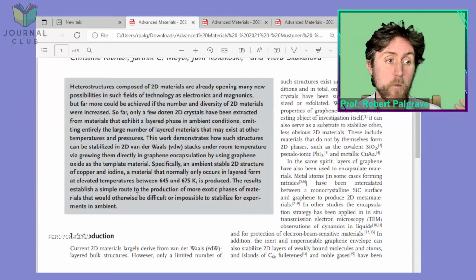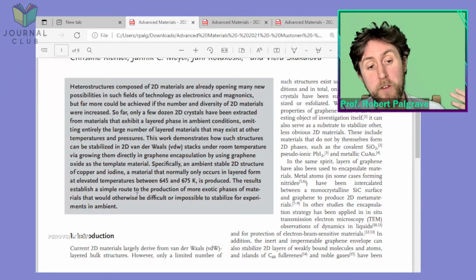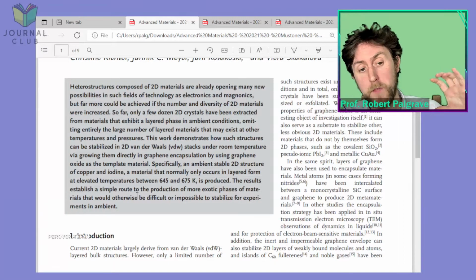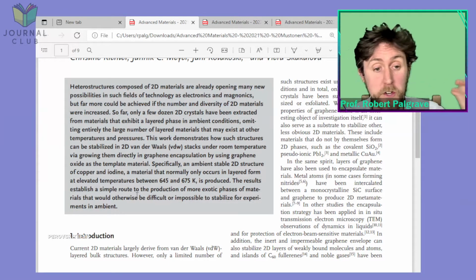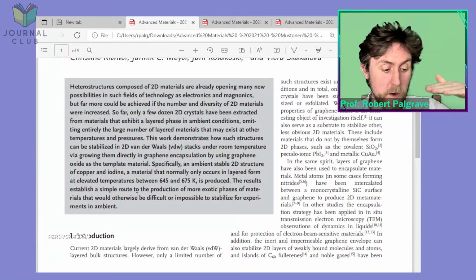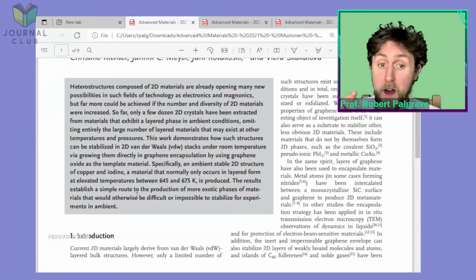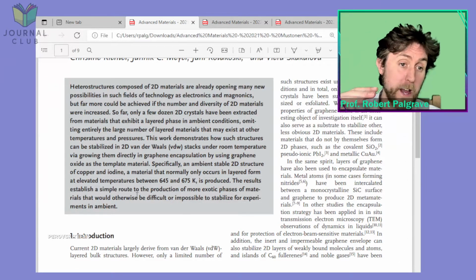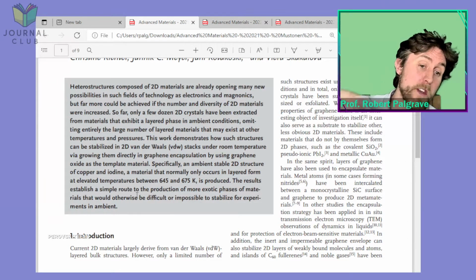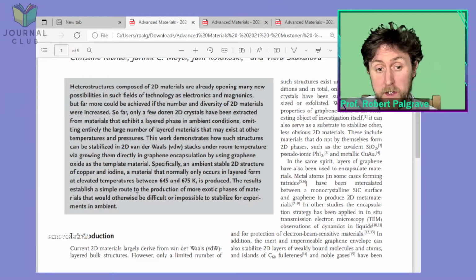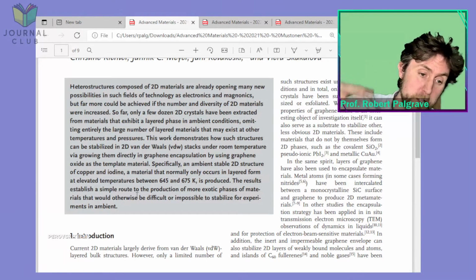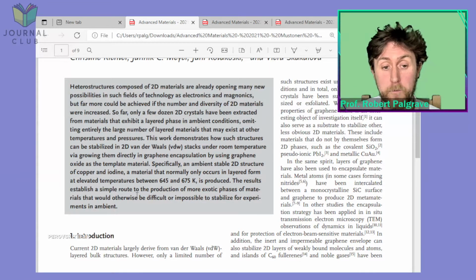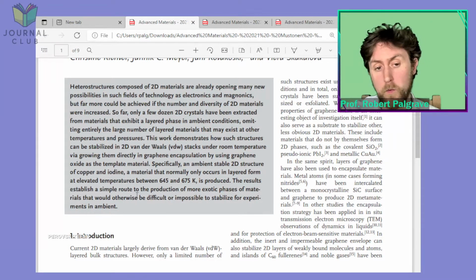So what they've managed to achieve here, as we'll see as we explore the paper, is they have a single layer of a layered material. This copper iodide, or cuprous iodide, does form a layered structure, but the difference is it only normally forms that layered structure at high temperature. The normal room temperature structure for cuprous iodide is a three-dimensional structure. It's based on zinc blende, so it's a cubic structure, which can't be separated into layers.